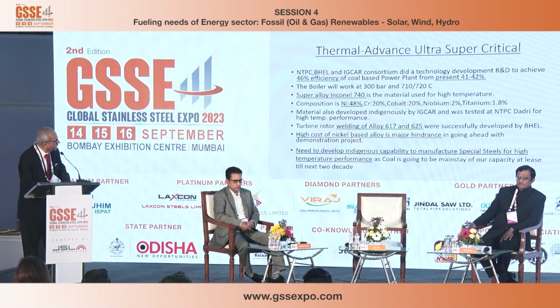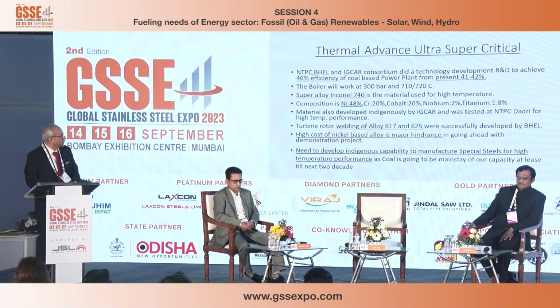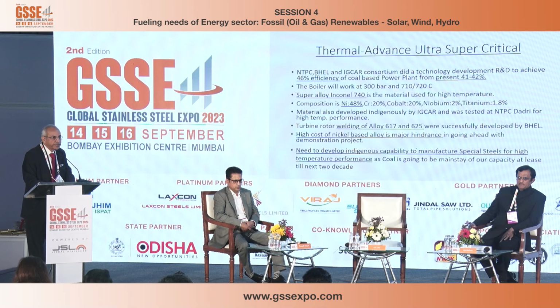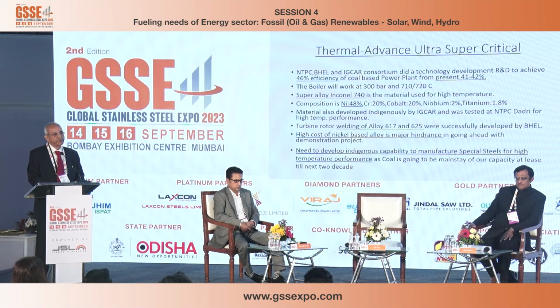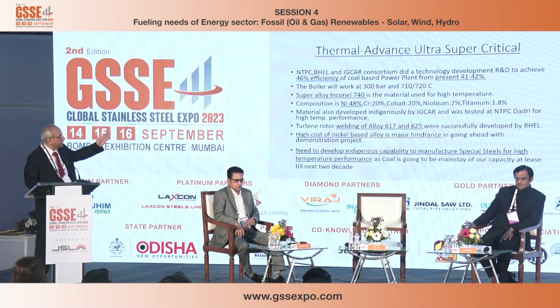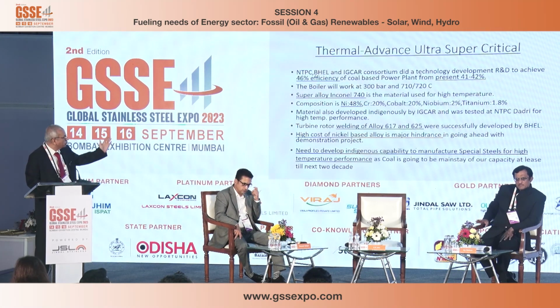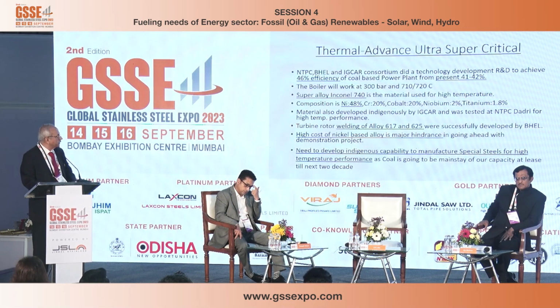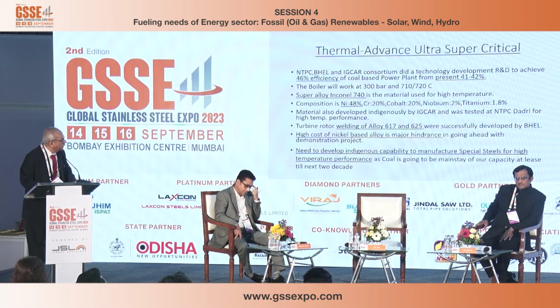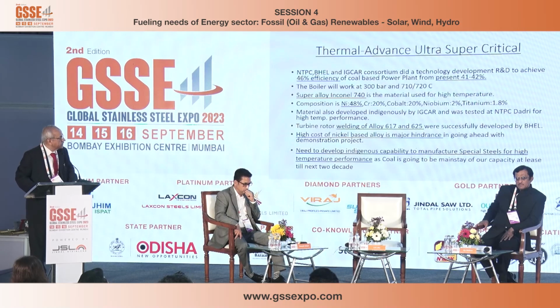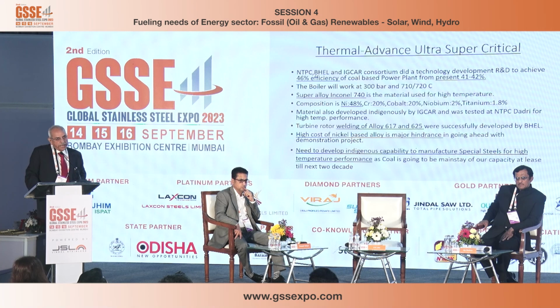The boiler design is made to work at 300 pressure and 710 and 720 degrees centigrade. Now this requires super alloy Inconel 740 material to withstand that kind of a high temperature. This composition is nickel 48%, chromium 20%, cobalt 20%, niobium and titanium in a small percentage. Now this material was also developed indigenously by IGCAR and was tested at NTPC Dadri for high temperature performance, and the performance has been successful.